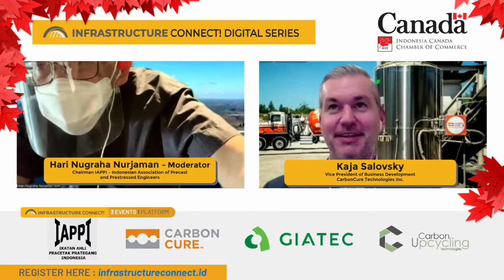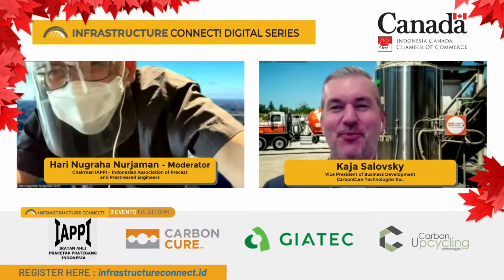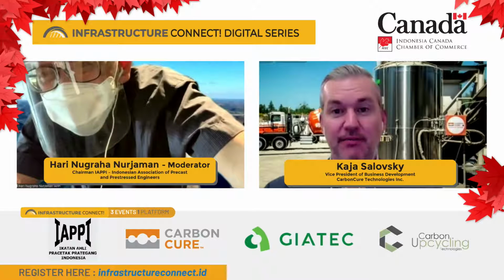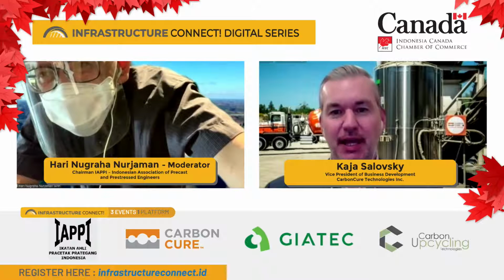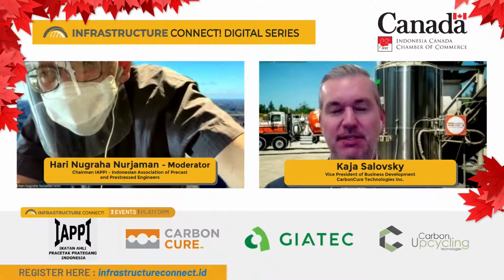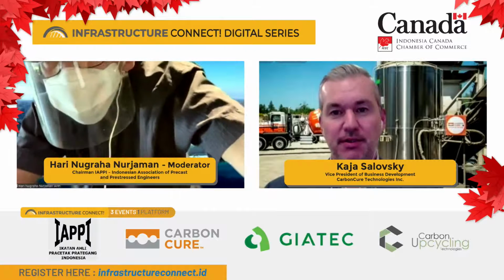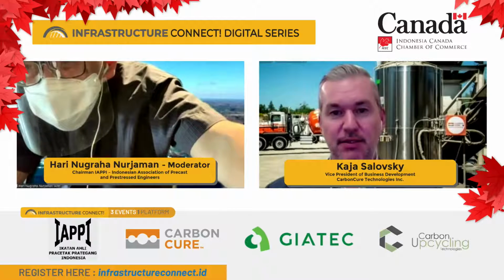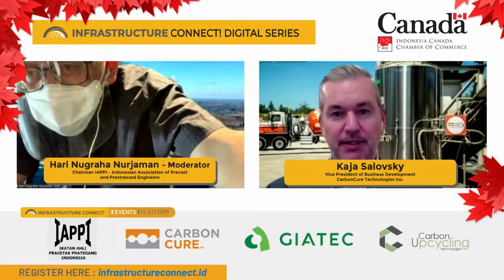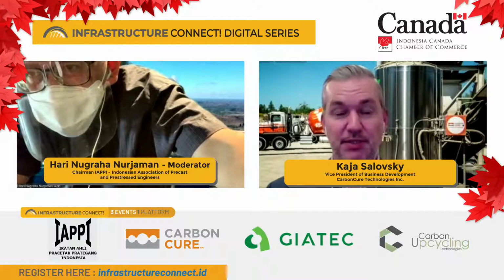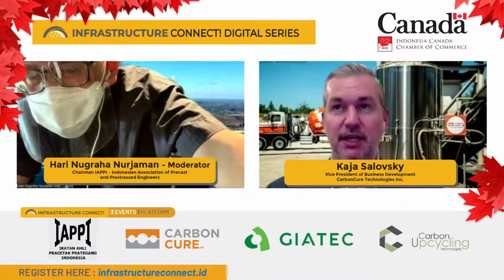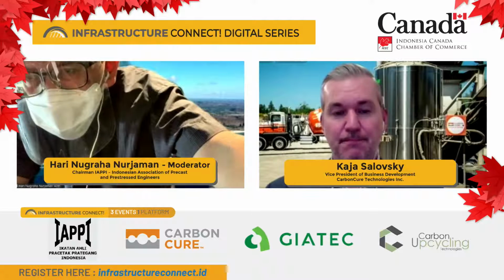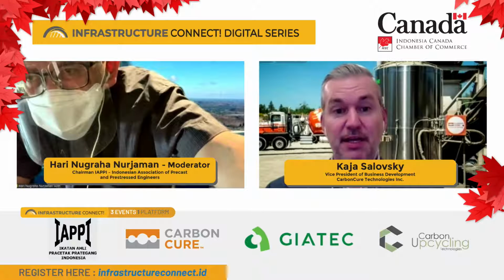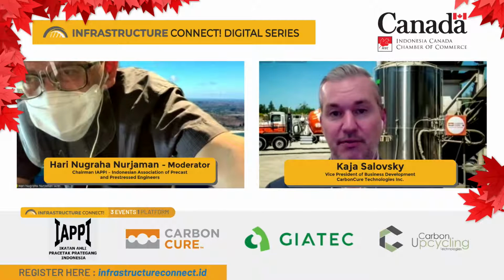Another educated and excellent question. What we are creating in the mixer, whether it's in the back of the truck or in the central mixer, is a nano calcium carbonate, so nano CaCO3. And the question compares the natural limestone that can be added into a cement blend or into the concrete as a supplementary cementitious material, similar to your fly ash and your slag. The size of the grain of cement that you're adding is still visible to the naked eye. The size of the particles that we're creating in the mixer are roughly 400 nanometers in size. So they are invisible to the naked eye.